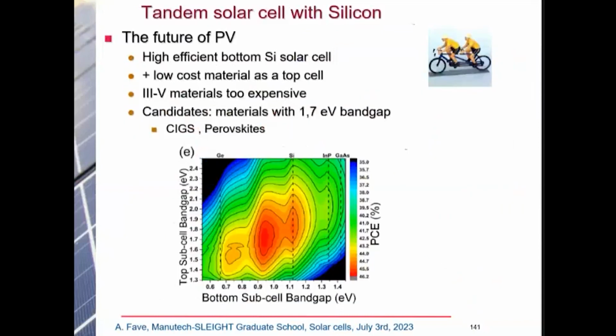So how can we simplify this technique and use all the development we did with silicon technologies in the past years? This is what we call the tandem, the silicon-based tandem solar cell. So, a combination of silicon plus another material. Here is plotted the band gap of the bottom cell, and here the top cell band gap. If we use silicon, it will be 1.1 electron volt. And here is the efficiency of the tandem cell you are going to build. You can see that there is an optimum here in red, corresponding to a band gap of 1.7 electron volt for the top cell material.